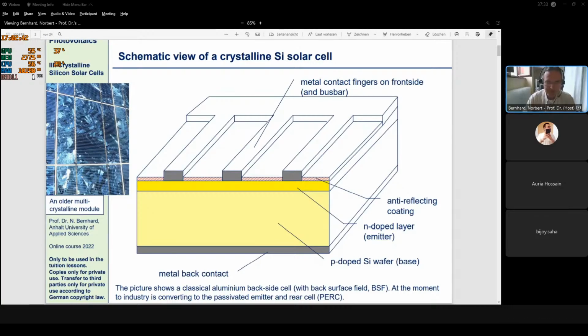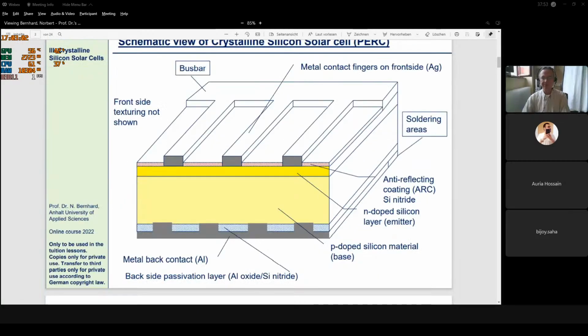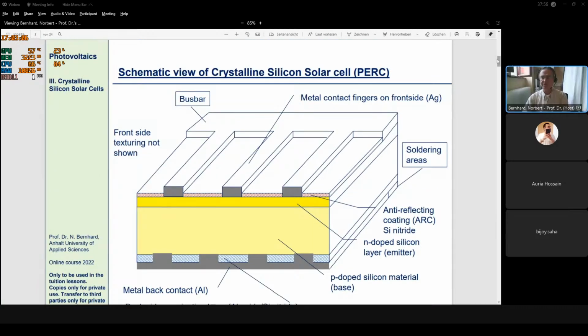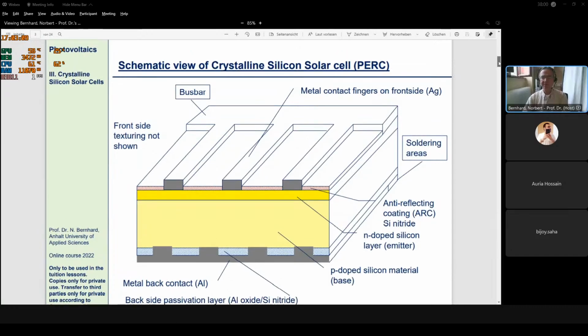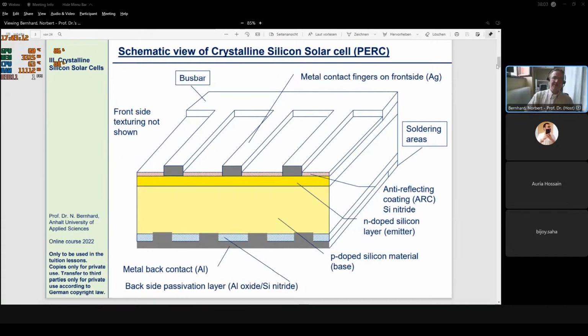And at the moment, the industry is converting to the passivated emitter and rear cell, the so-called PERC cell, which we see on the next page. This picture you have also seen already. This is now the PERC cell. The conversion of the whole industry, I would say, is done to roughly 60 or 70%. That means roughly 60 or 70% of the volume production of crystalline silicon is already this type of cell. The rest is still the previous one. And the only difference is at the backside of the cell.